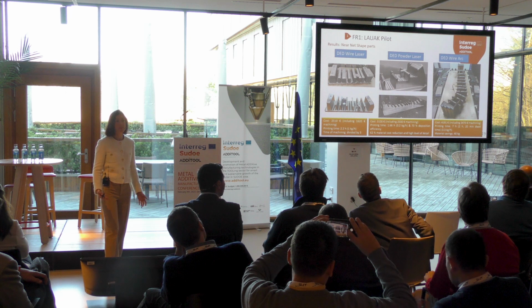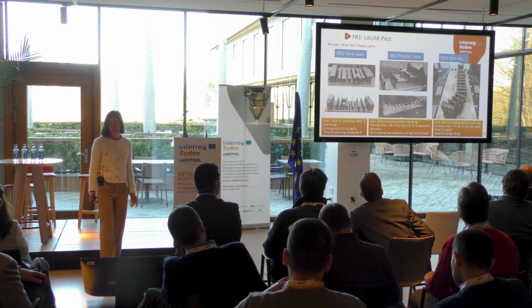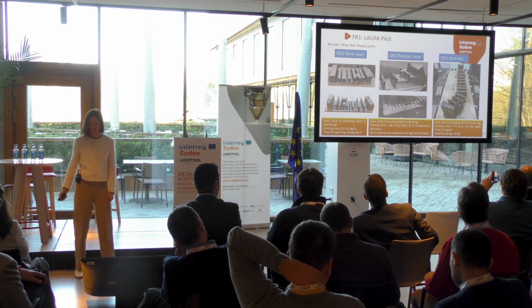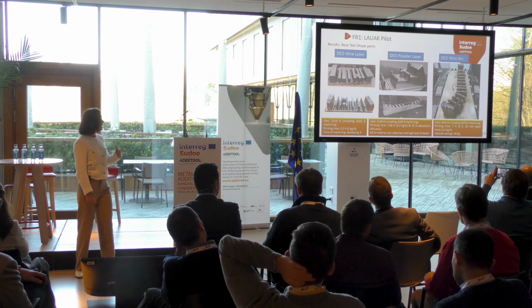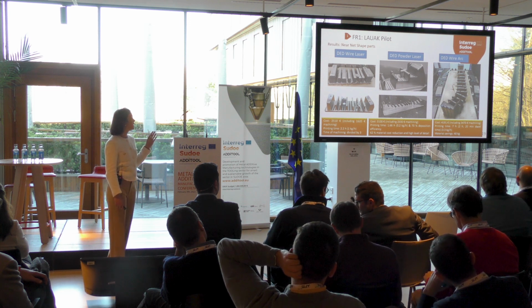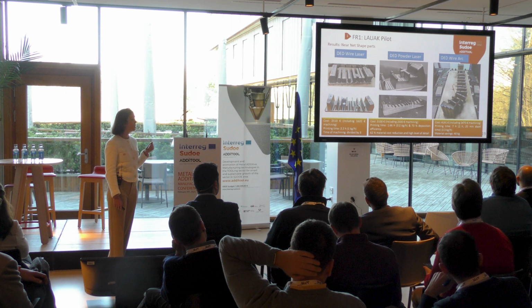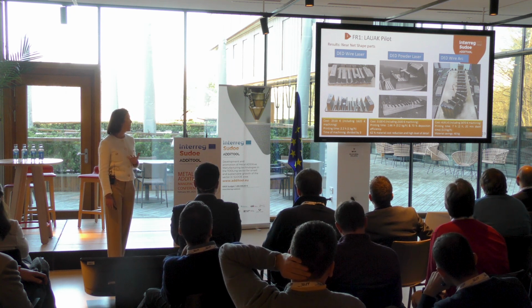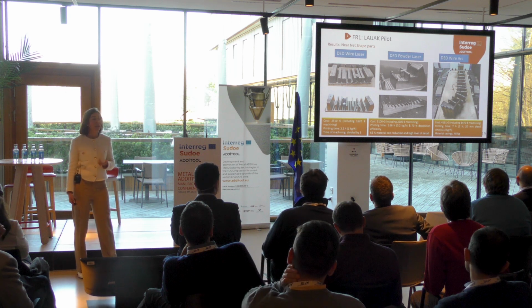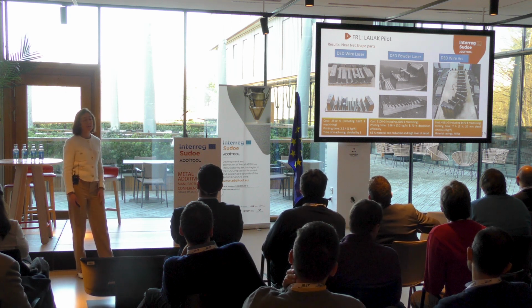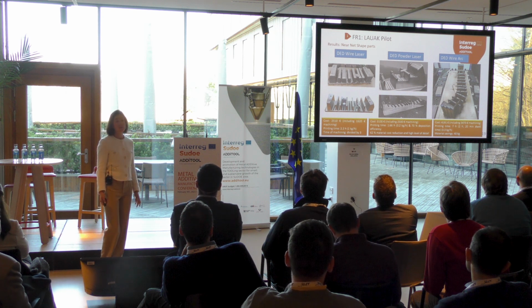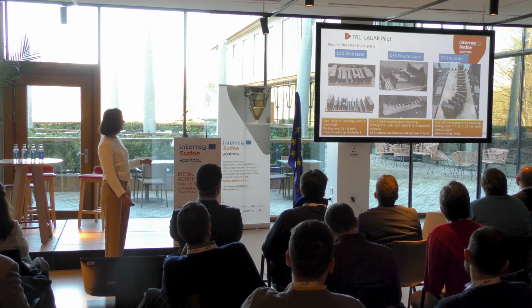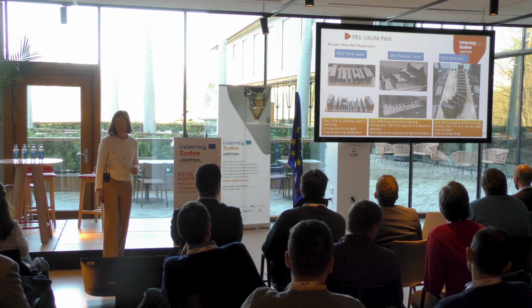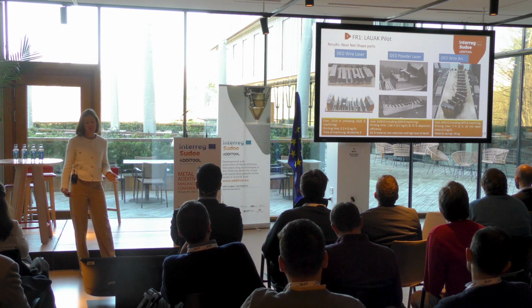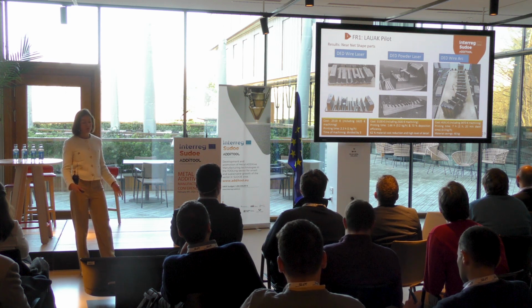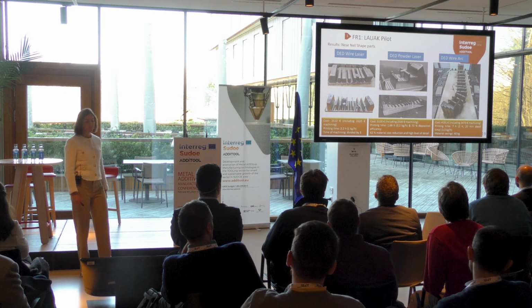Again being more or less the same percentage for the machining step. The printing time is 7 hours, but I wanted to highlight the time of 2 hours and 20 minutes that belongs to interlayer dwell time. This is a time that can be optimized or minimized by choosing other cooling strategies. We wanted to highlight here the high deposition rate and the material savings compared with conventional machining of a block, which was 40 kilos.